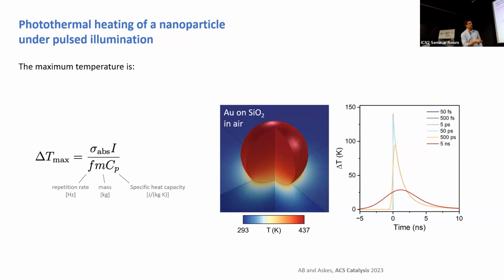Like at 5 nanoseconds, the heating is so slow that it overlaps with the cooling, which is of the order of nanoseconds. But for the rest, we can always get this nanoparticle to the maximum temperature because the cooling is so slow that any pulsed laser source more or less will give us the maximum temperature. Okay, this is how we conceptualize how hot we can make nanoparticles in the lab under CW and pulse.